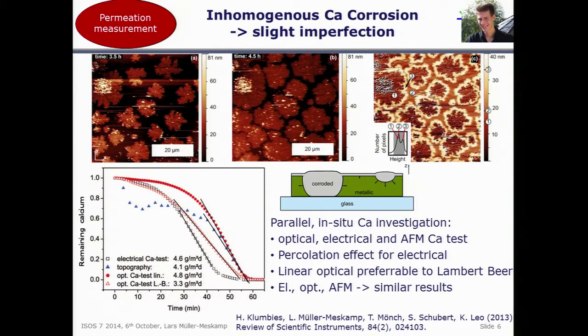But if we do a comparison, so we have done all methods in parallel. So this is the optical calcium test. And here you have one slope. This is the AFM, just averaging the surface area which is corroded, and it gives you a slope. And this is the electrical calcium test. So it's all the same device measured at the same time in situ with all three methods, and you see basically these three slopes are the same. This one is a different optical way to evaluate. So it's pretty valid, although it's a bit inhomogeneous. Okay, so the calcium test is always good for surprises.